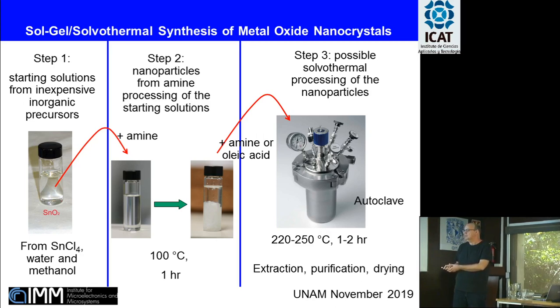which is transparent at room temperature after being molten. We inject with the syringe the precursor inside. This is all. All those words are condensed in this simple procedure. Then we take this precipitate, we disperse it in oleic acid or oleoylamine, depending on the system, and we make a solvothermal treatment. We need quite mild conditions, something like 220, 250 degrees C for 1-2 hours. Then extraction, purification, drying, and so on.